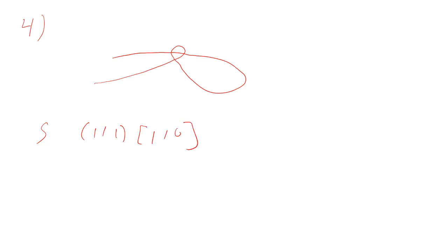The {111}<110> is the observed slip system instead of {100}<110>. And I think basically everyone got this, that attempted it. If you think about what goes into the resolved shear stress, the Burgers vector is shorter and the plane spacing is larger. So these dislocations can move, whereas these ones are sessile.